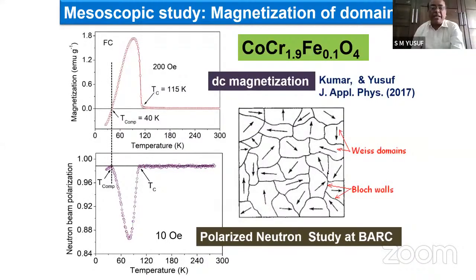Here it is the magnetic domains. Now, here is the magnetization as a function of temperature. You see this, this is the magnetic ordering temperature, Curie temperature, or rather Néel temperature. And then magnetization is maximum, but then decreases, goes to 0. This is the compensation temperature, and then goes to the negative side. Now look at the below, the neutron depolarization study, that is neutron beam polarization, meaning transmitted neutron beam polarization.